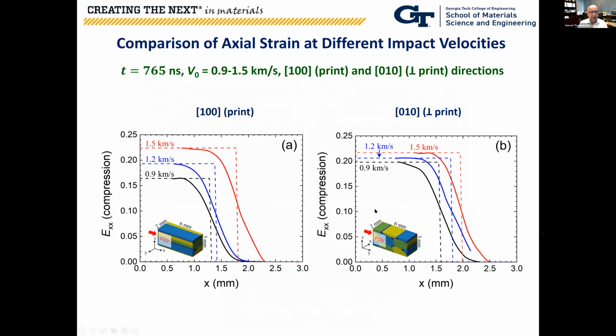If you look at it in the context of what happens at different impact velocities and as a function of the print direction, this is for the 100 print direction, and this is perpendicular to the print direction. Notice what is happening here—this is very interesting. The normal strain component epsilon xx at different impact conditions reaches a peak anywhere from about 17% to about 22% at these 3 different impact velocities, and then as a function of distance, it tapers down to 0.